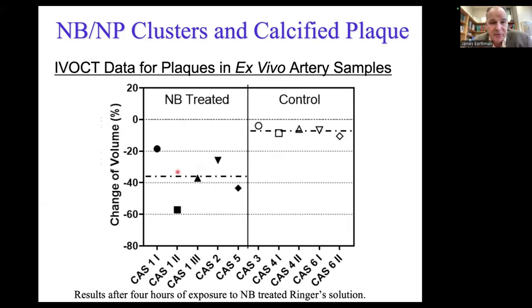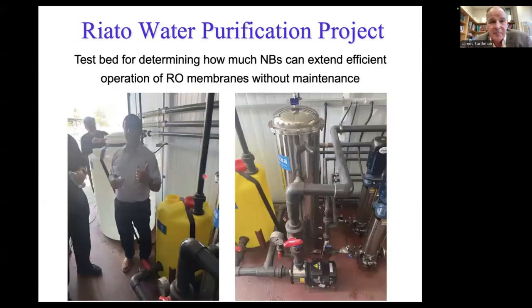And here we did it again. This is for 3 hours. This is after 4 hours with nanobubbles for 5 different samples. This is 5 control samples. And again, big difference in reduction of that plaque.